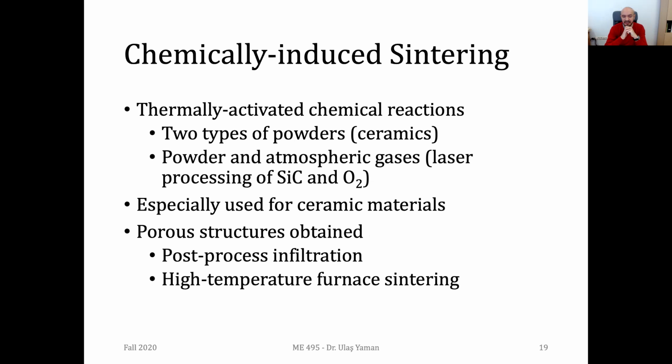And as you know, I think some of you may remember the infiltration process from ODTÜ. You need to put your part into a furnace, and the furnace should also be filled with the secondary material. Once you increase the temperature, the secondary material will be melted, and it will go into these porous regions and fill your part completely.